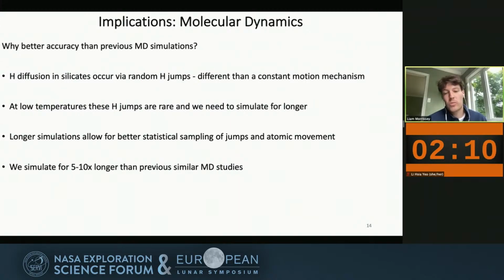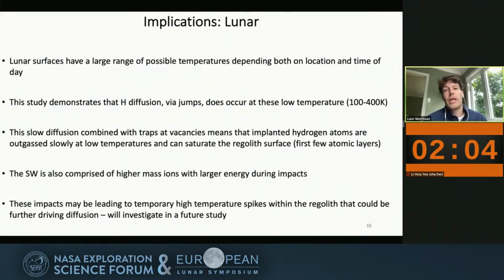We think that because we're simulating for longer and sampling better, we're actually getting a better accuracy. And finally, there's also implications from a lunar point of view. We know that lunar surfaces have a large range of possible temperatures, depending both on the location and the time of day. What this study demonstrates is that H diffusion via jumps does occur at these low temperatures. And because of this slow diffusion combined with traps at vacancies, this means that implanted hydrogen atoms are likely outgassed slowly and can saturate the regolith surface.